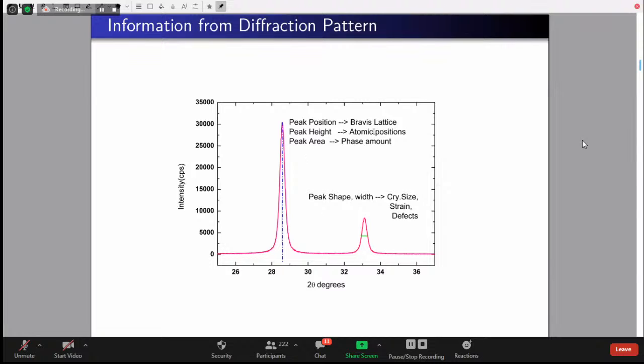Right. So here intensity is related to atomic positions, and the peak area, the area covered by one single peak, belongs to the phase content. Suppose we have two different materials, let us say cerium oxide plus zirconium oxide, added together. They can both have a similar kind of peak at a similar place, but if the two materials are together, their peak intensity is going to be very, very different. So when we do quantitative analysis for X-ray diffraction, we look at the peak area, which belongs to the phase content, that is, how much of a particular phase is available.